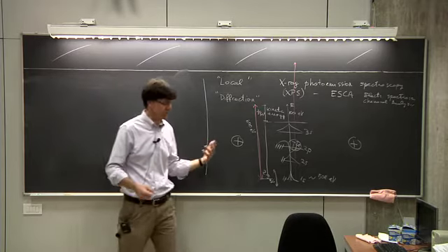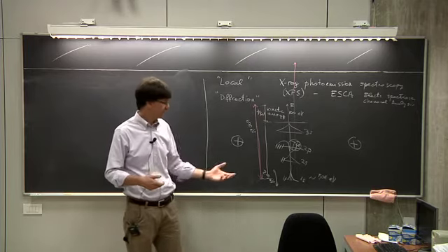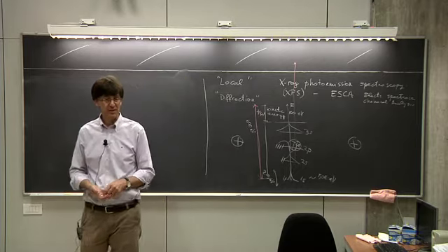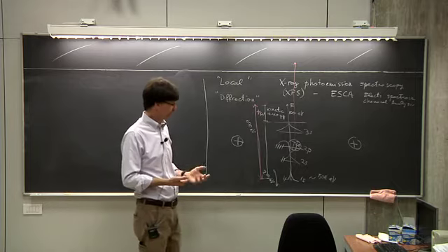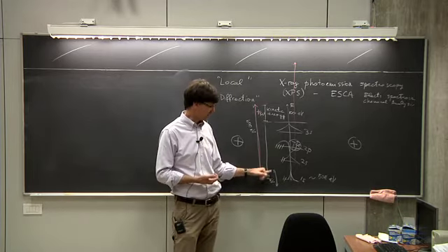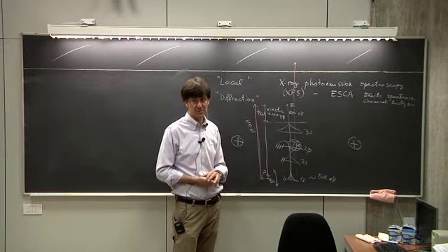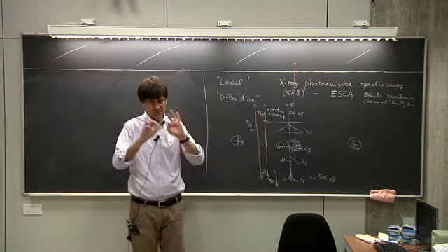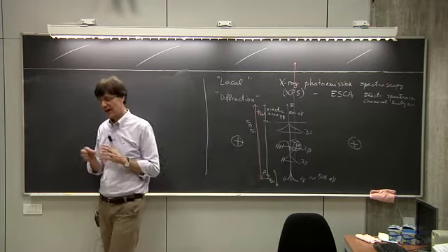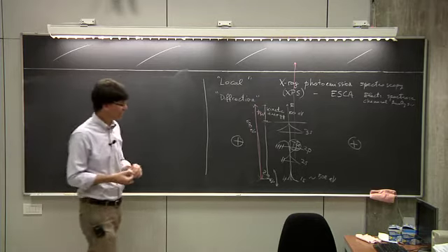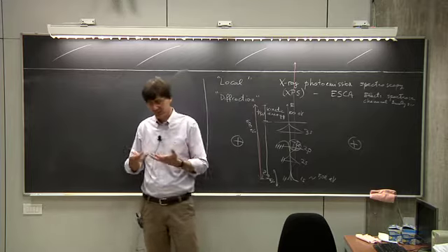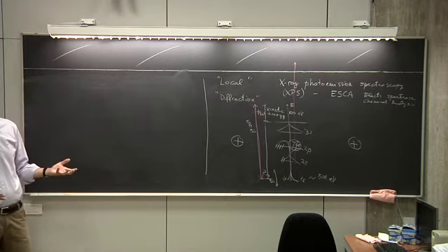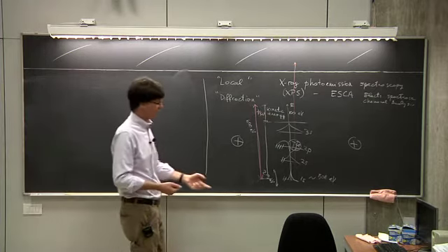It's based on some previous knowledge about changes in the binding energy as a function of the local configuration. It's not something that you can immediately tell how much these energies change as a function of the nearest neighbors. But it is a parameter that certainly changes due to the local environment. That's the main point of this story. How you then correlate precisely this change to the local environment is a very difficult exercise that requires you to know examples for which the structure is known and to know how the binding energy changes in structures that are known.